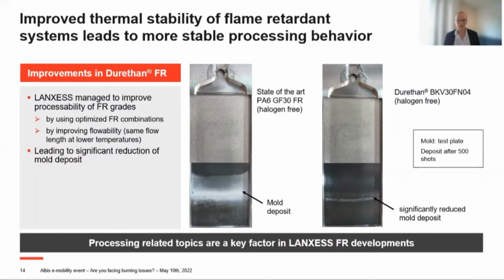And what you see here is a comparison of a state-of-the-art PA6 GF30 with a halogen-free flame retardant system on the left side, and our Durethan BKV30FN04, which is also a PA6 GF30 with a halogen-free flame retardant system. But within this grade, we managed to improve the processability of the flame retardant system by using optimized combinations of flame retardant systems and also by improving flowability. And by doing that, we managed to significantly reduce the mold deposit, because one of the challenges that customers often see with flame retardant materials is that due to the smaller processing window and also due to the additives that are within the flame retardant package, you see some mold deposit, which you can maybe see here on the picture, on your mold.